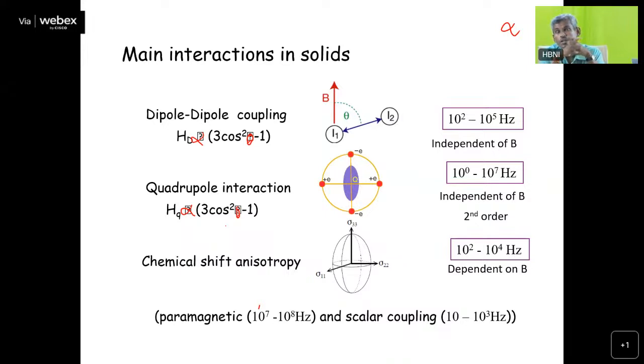So this quadrupole interaction has multiple terms, and multiple terms have multiple radial terms and multiple angular terms. At least 3 terms, first order, second order, third order terms, are there in the case of quadrupole interaction. At least the first 2 terms have an angular dependence of 3 cos squared theta minus 1, where theta is nothing but the angle the bond vector makes with respect to the applied magnetic field.